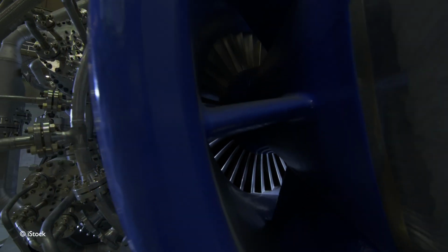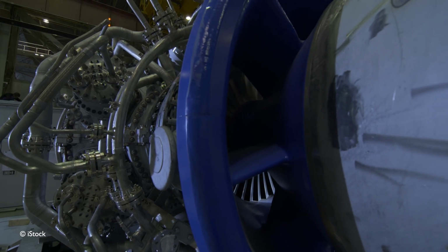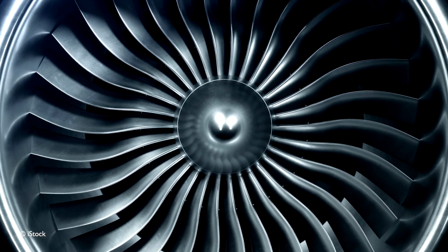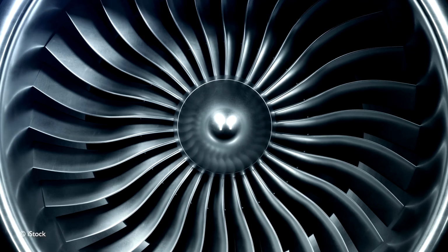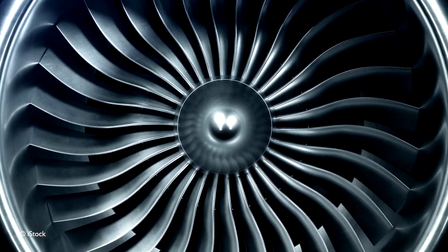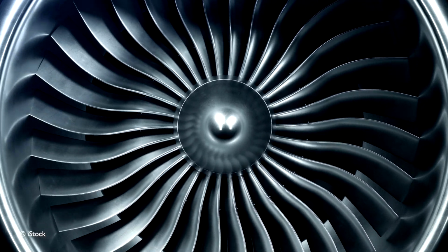Zircon and zirconia already make contributions to various sustainable applications. We have, for example, the use of yttria-stabilized zirconia in thermal barrier coatings. So these are coatings that are applied on turbine blades, for example. And yttria-stabilized zirconia has a very low thermal conductivity, and it helps to protect the metal components of the gas turbines, allowing those gas turbines to be run at a higher temperature.